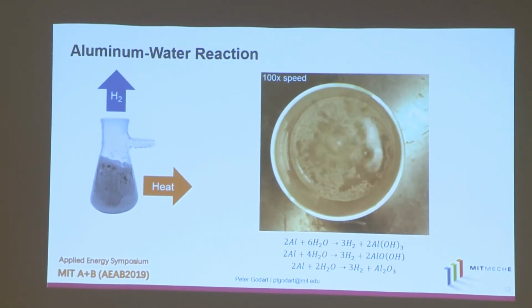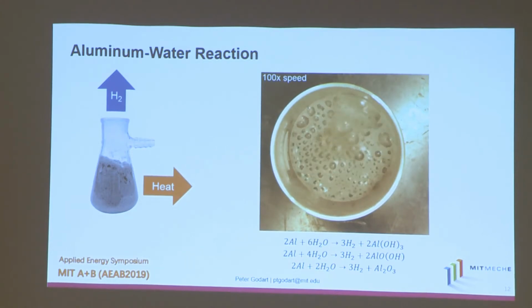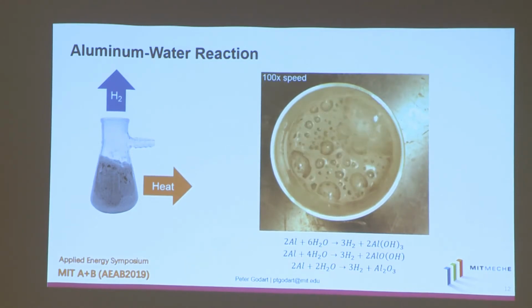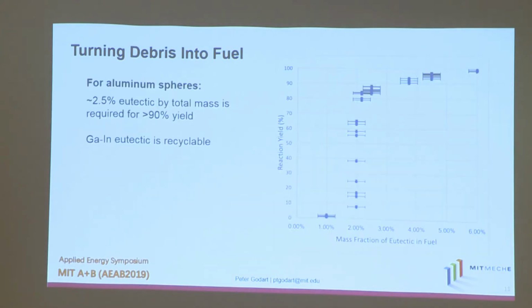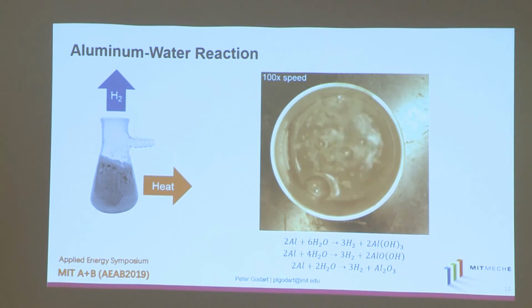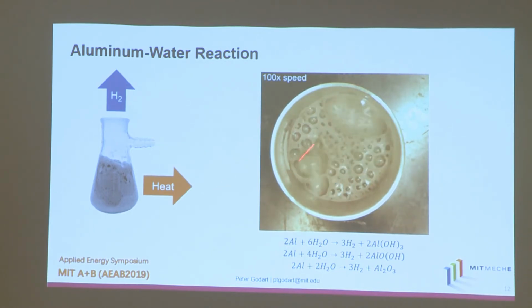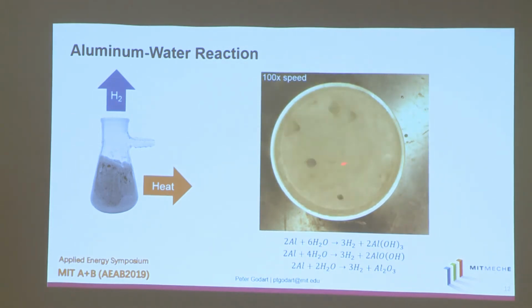So now that we have this fuel, we can react it with water to produce hydrogen, and thermal energy is released in that process. And you can see the sped up video here. It'll loop around in just a second. But we add the aluminum. So let me back up, play one more time. We combine aluminum and water in some sort of vessel. You see immediately hydrogen is produced. We're producing some byproduct, which I'll talk about in a second. And you can see that the thermal energy is actually boiling off the remaining water before the rest of the aluminum can react. So it is an incredible thermal energy release as well.